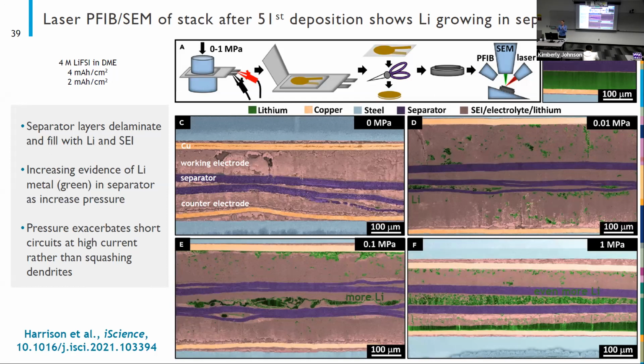And so by having to deposit lithium under pressure, you induce strain in the crystal lattice of the lithium. But if you deposit at no pressure, you do not do that. But that is still ex situ, where you have cycled it back to low pressure. And all this is happening at high pressure. So it makes sense for you to do those measurements at high pressure.